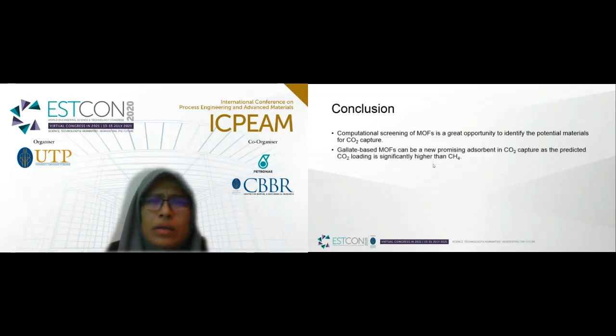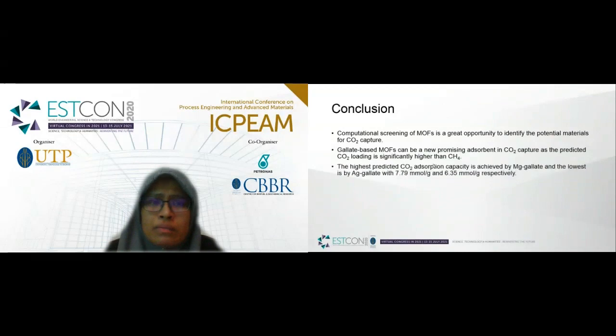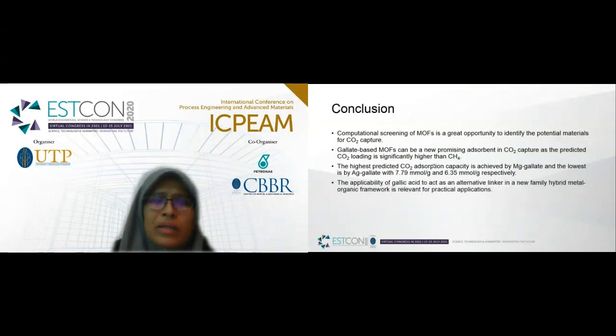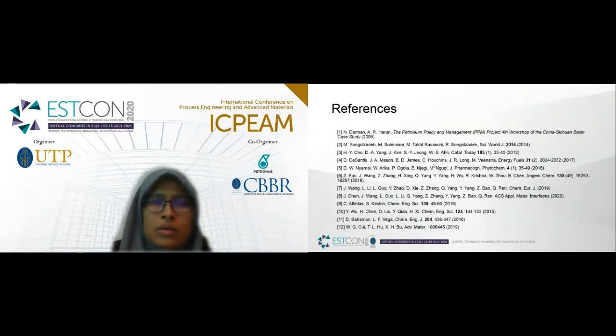Gallate-based MOFs can be a new promising adsorbent in CO2 capture as the predicted CO2 loading is significantly higher than CH4. The highest predicted CO2 adsorption capacity is achieved by Mg-gallate and the lowest is by Ag-gallate, with 7.79 millimole per gram and 6.35 millimole per gram respectively. The applicability of gallic acid to act as an alternative linker in a new family of hybrid metal organic framework is relevant for practical applications. So these are the references,